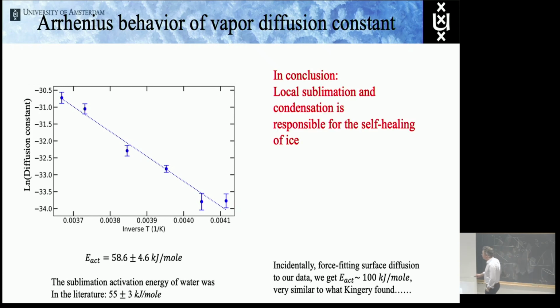Okay, so sublimation condensation gives an activation energy, and the activation energy is something like 58 kilojoules per mole. If you look at the sublimation activation energy, because the condensation is actually energetically easier, you find 55. And so we are really convinced that this is the mechanism behind the mobility of ice molecules on the surface of ice.